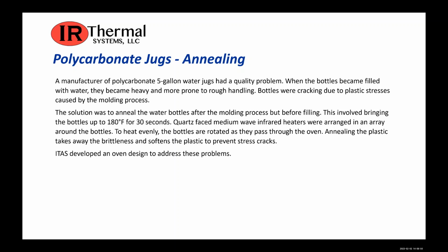The solution was to anneal the water bottles after the molding process, but before filling. This involved bringing the bottles up to 180 degrees for 30 seconds. Quartz-faced medium-wave infrared heaters were arranged in an array around the bottles. To heat evenly, the bottles are rotated as they pass through the oven.